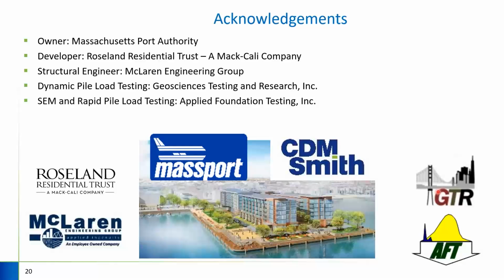I have one question that came up, and we have time to do that already now. In your signal matching on the dynamic load testing that was done, did you detect any defects along the tested piles? So from the PDA testing, the signal matching was very good. We did not see any significant defects. You did note some in the areas where the two pile repairs were conducted, a slight mismatch in the signals, but that was obviously due to the repair itself. And so below the mud line, we did not see any deleterious effects from the time that those piles have been installed over the last 70 years.